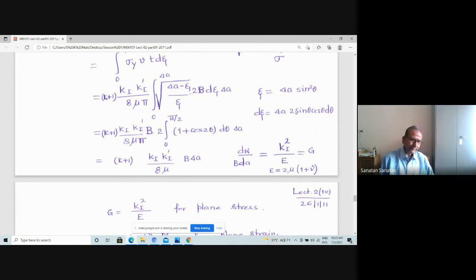He said that yes, at the point of onset of crack extension, the extension takes place when that energy availability per unit crack extension is a critical value, and that value is actually K1 square by E, and Griffith's energy is that, so that is G. So Griffith energy is given by the stress intensity factor, the crack tip stress field parameter K1, which is called stress intensity factor, not stress concentration factor. That is the parameter which actually appears as a constant amplitude term, K1 by root 2 pi r into a function of sine theta. So this K1 is the stress intensity factor at the crack tip.